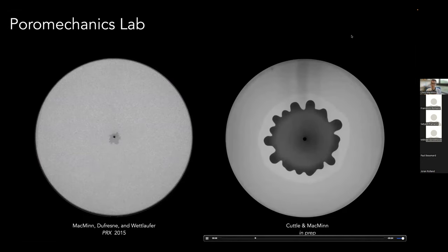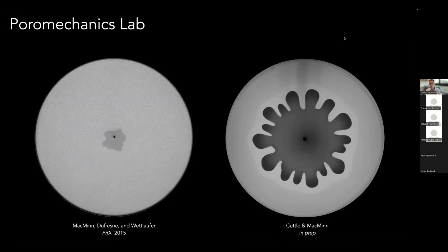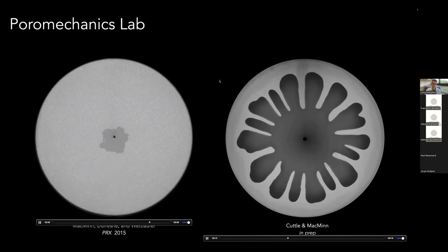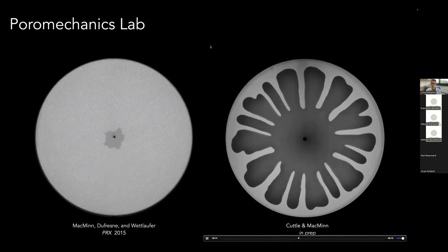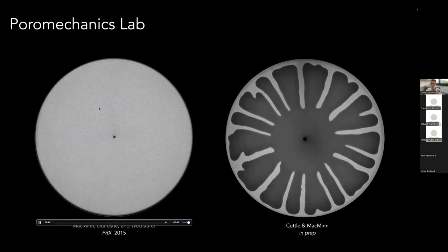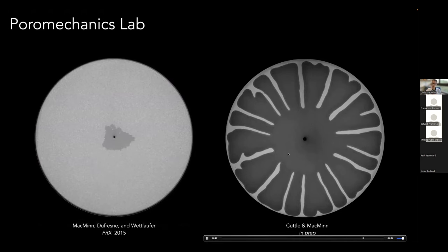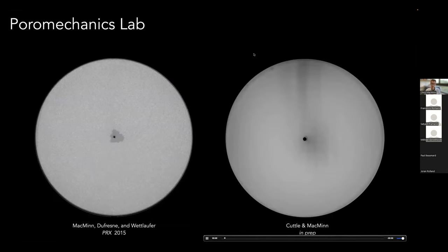And what makes them, in my mind, high resolution is the fact that in both cases, we can actually infer a lot qualitatively and quantitatively about what's happening by image processing. So in the case on the left, we can follow the particles by using individual particle tracking and calculate a displacement field. And in the case on the right, since we've dyed the invading fluid, we can actually use the local brightness of the invading fluid to measure quantitatively the gap thickness in that region.